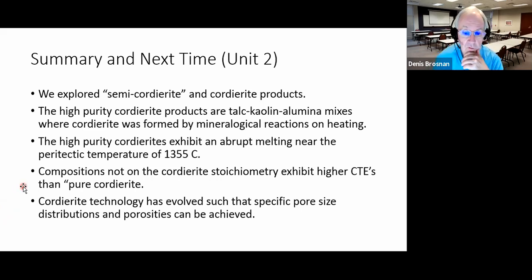Let's give a summary. So we explored semi-cordierite and high purity cordierite. High purity cordierite was the more interesting one for us. We used talc, kaolin, alumina mixes to meet the compositional goal. We talked about the mineralogical reactions on heating, and particularly we talked about the peritectic temperature being around 1355. So in traditional quarry ware, you have to be careful not to exceed that temperature unless you've done something to influence the amount of glass phase present. Otherwise, you can get deformation of your ware.